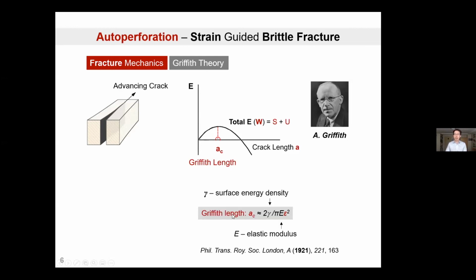Griffith then went on to calculate analytically what the Griffith length is as a function of other material parameters. Specifically, he pointed out in this formula that the Griffith length scales inversely proportional to the square of the specific strain at a given location of the material. This is interesting, meaning that increasing material strain gives us a tunable factor that we can use to control the Griffith length, hence to control the breakability of a material. So how does that square when we look at two-dimensional materials?